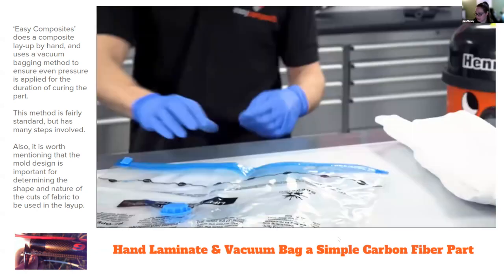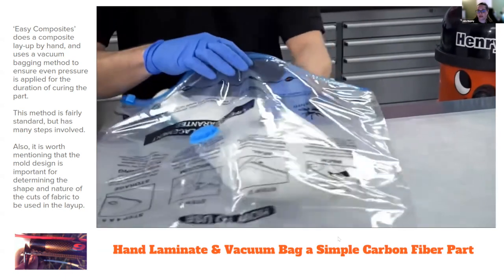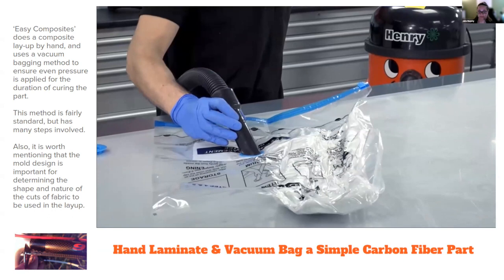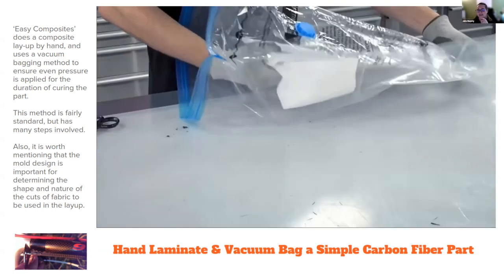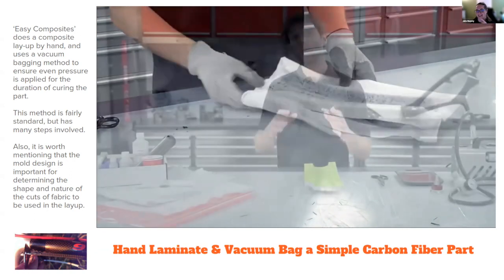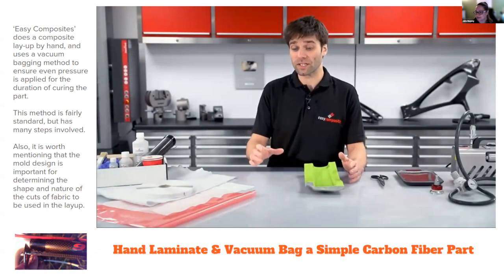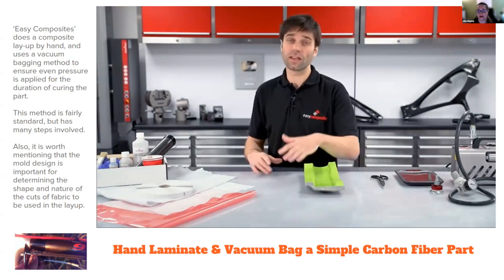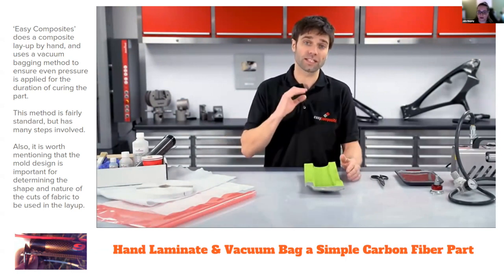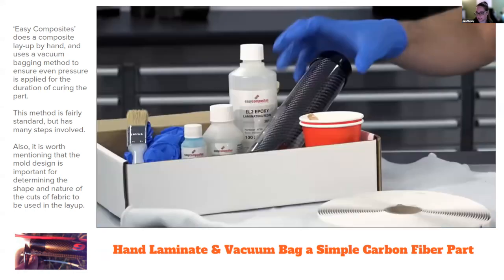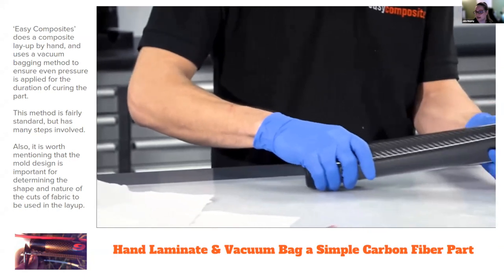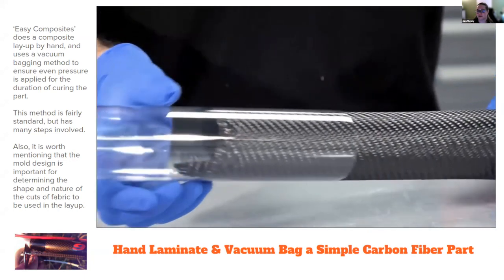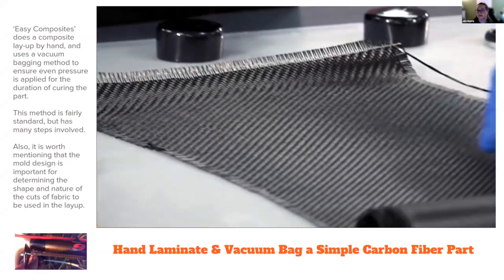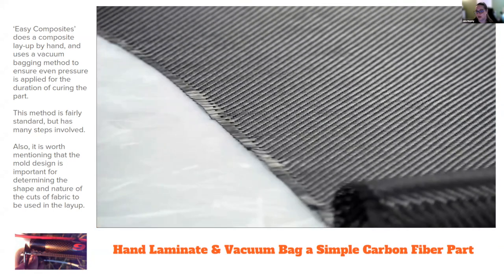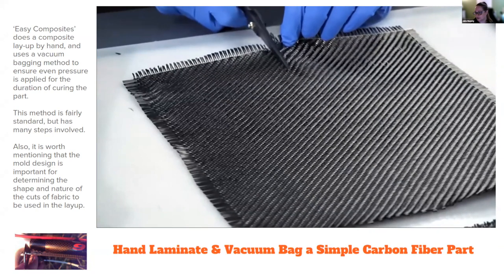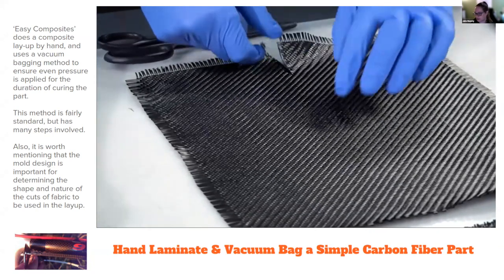The thing that I recommend is if you're going to do this and you want to do a fiber-based layup, they used a vacuum cleaner for this to see how it would do, and it actually did pretty well. So this is something you can fudge together at home if you want. But as I was saying, if you're starting out with this, starting with a really flexible fabric like burlap that goes in all directions relatively easily is going to be a little bit easier to start with the entire process. This stuff has no real desire to conform to curves. And so you have to fit it pretty carefully.